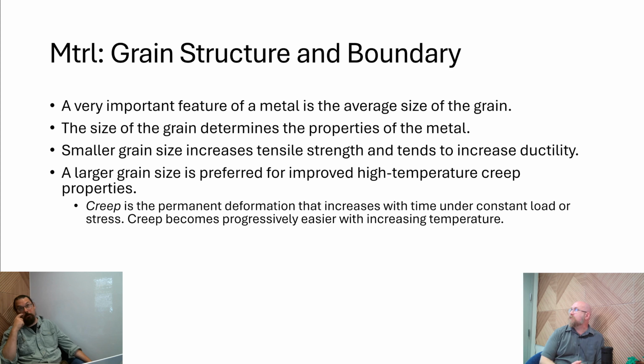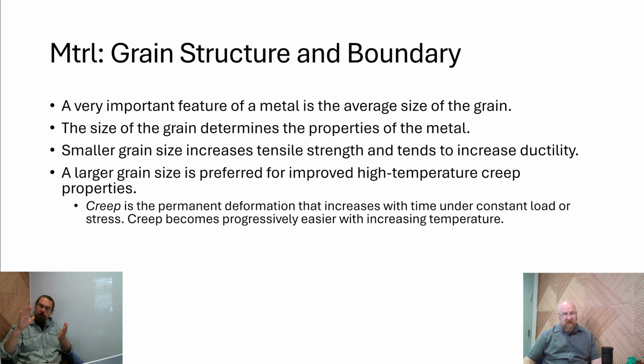And this is not easy to do. It's not. That's part of the reason why, when you look at a turbine blade, it's this little piece of metal that might be just a couple inches wide and maybe a couple millimeters thick, and yet it costs thousands of dollars to manufacture. It's because they have to control the temperature and atmosphere for a long period of time to get that continuous crystalline lattice, to that size. So it's a very finicky process.